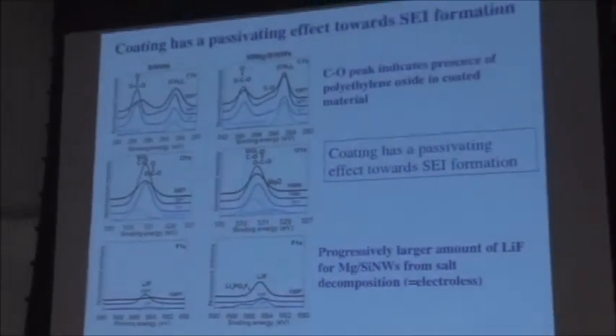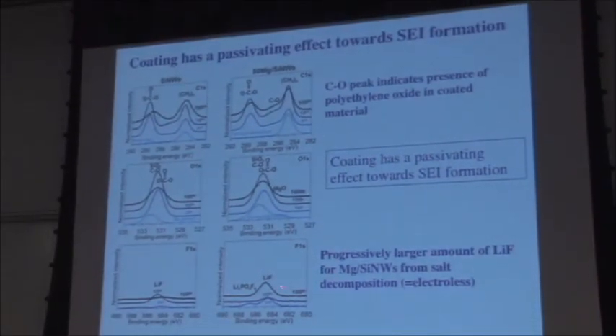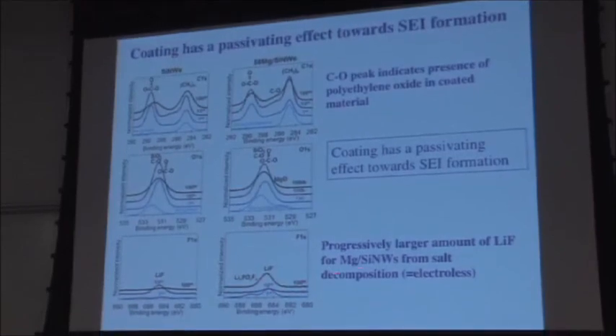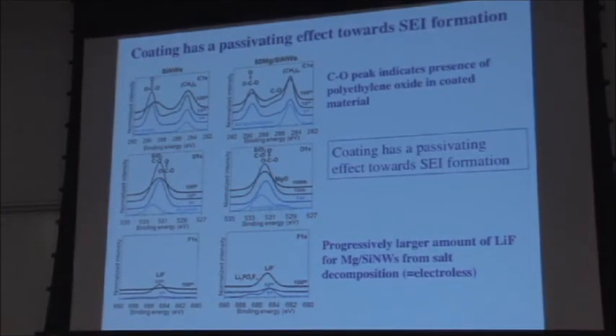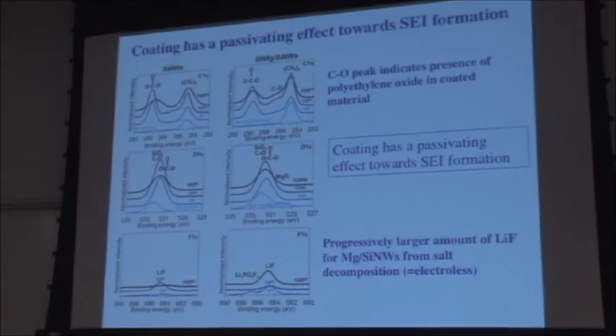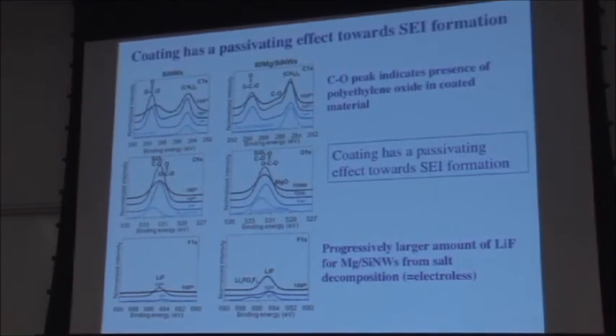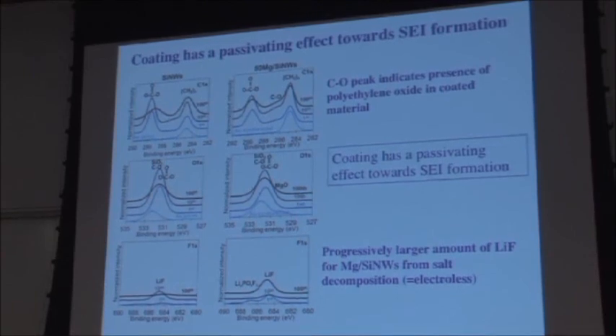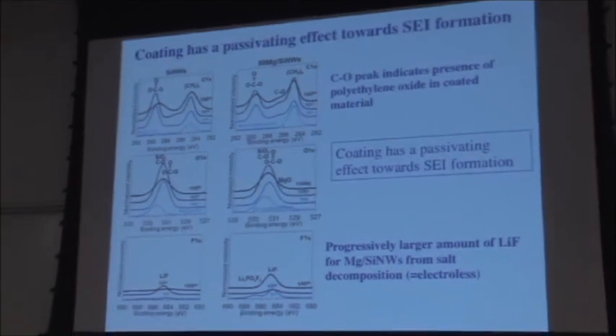in the Coulombic efficiency. So it's not necessarily that wonderful of a finding in terms of here's the solution, because A, the Coulombic efficiency is still not very good, and B, you're still sucking up lithium, but it really gives hints of how you can start playing around with different coatings to both improve the lifetime of the material and perhaps, with a different type of coating, change the structure of the SEI layer. Notice the silicon itself doesn't actually participate in the SEI layer formation.